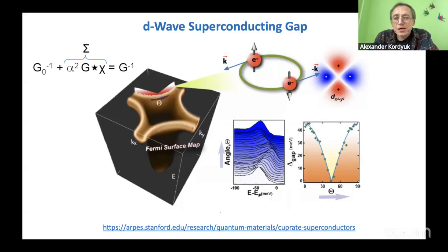This is because this superconductor showed that the superconducting gap is not uniform around the Fermi surface, or not uniform in, let's say, reciprocal space, because it has some symmetry which is called D-wave symmetry. This means that at some portion of the Fermi surface it is maximal, at some portion it goes to zero. Therefore, when you integrate everything in a tunneling experiment, you have all these features, spectra of interaction shifted by different amounts. Therefore, all the picture is smeared out, and it is difficult to extract any information.